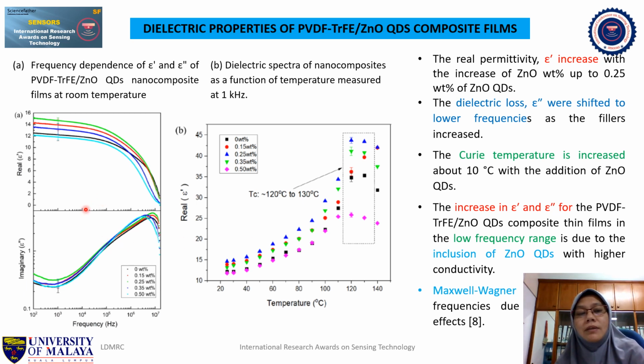So the increase in real and imaginary parts of the permittivities of this composite at low frequency range is due to the effect of conductivity of zinc oxide quantum dots. And we can also see in this figure that the Maxwell-Wagner relaxation is observed at low frequency due to the interactions at the interface between zinc oxide quantum dots and the polymer host.